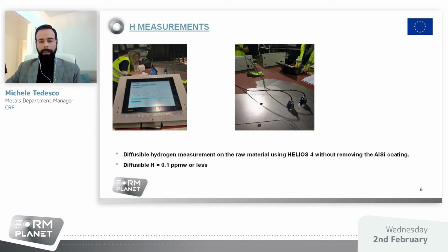Before stamping the component, we did together with Latomec the measure of diffusible hydrogen on the raw material as we received in our facilities. To do that, we used the Helios 4 system without removing the surface coating, and we found that the material was very clean, very poor diffusible hydrogen was detected, less than 0.1 part per million.